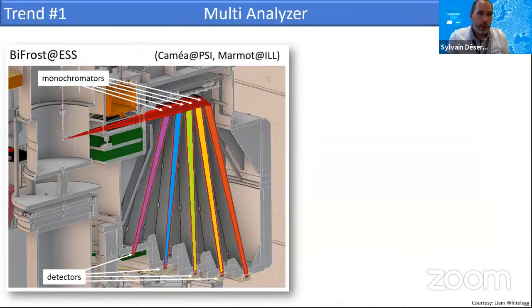Now I move to trends, and I begin directly with the trends about instruments. Now many instruments are using a multi-analyzer principle. So I took the example of Bifrost at ESS, which is an inverse geometry spectrometer, where the principle is that the neutrons scattered from a sample located here will transmit through a set of 5 monochromators, and each monochromator has a different angle. So according to the Bragg law, the neutrons with the right wavelengths will be reflected. I use different colors here to show this, and they will be collected at the bottom of the tank with